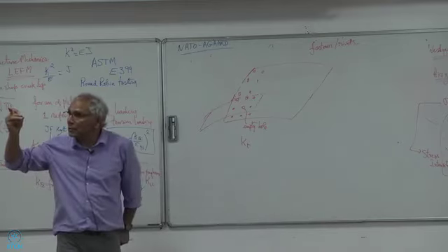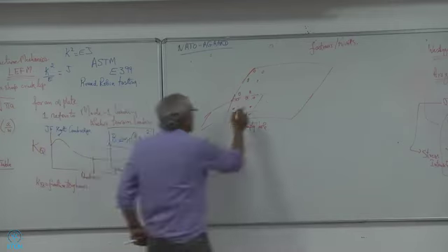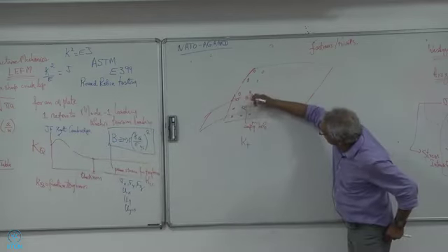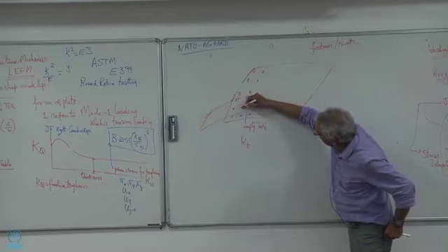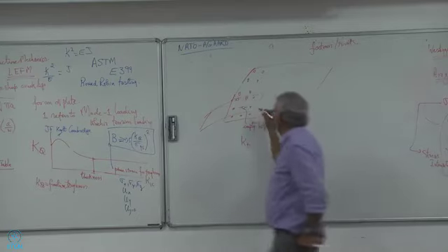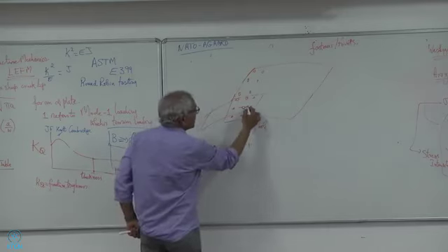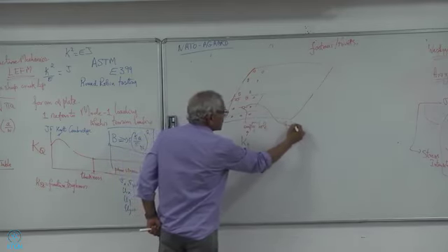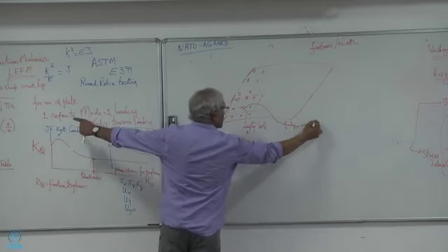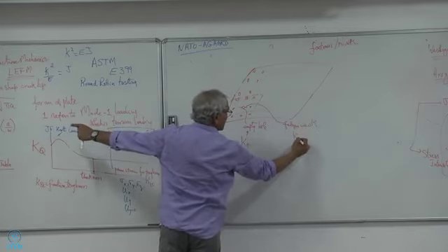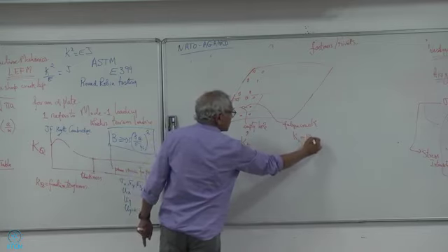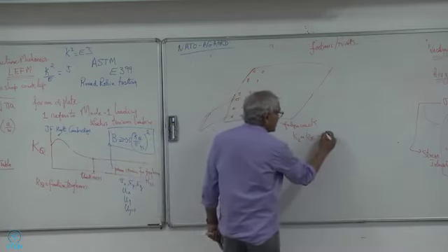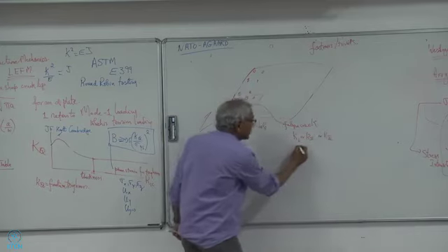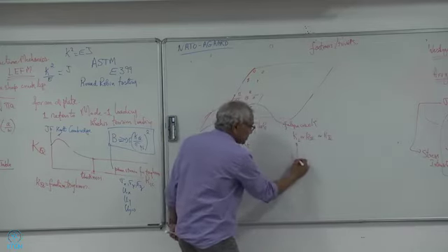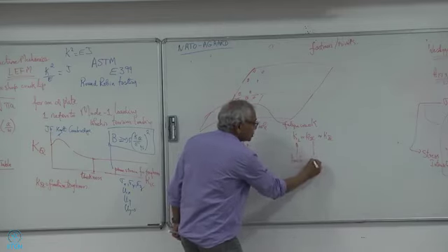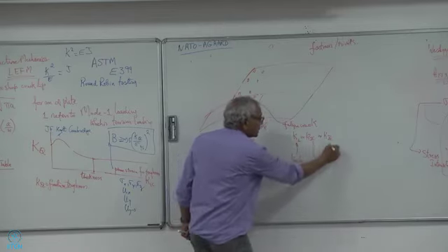But once a fatigue crack starts there, so once this empty hole, you start a fatigue crack. So here, K sub T, but once the fatigue crack starts, then you go to your K1 or K2 or even K3. So K1 is your tensile mode, mode 1. This is mode 2, which is your shear. This is your torsion.